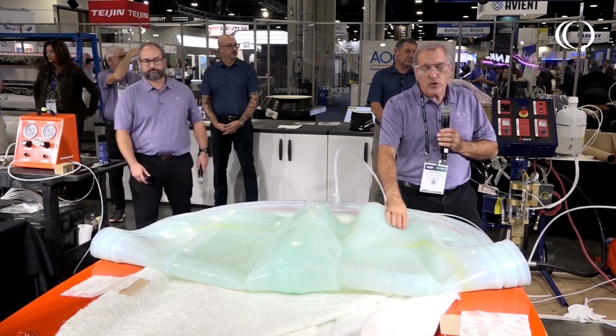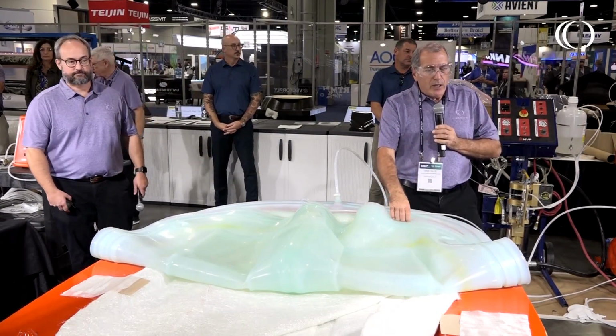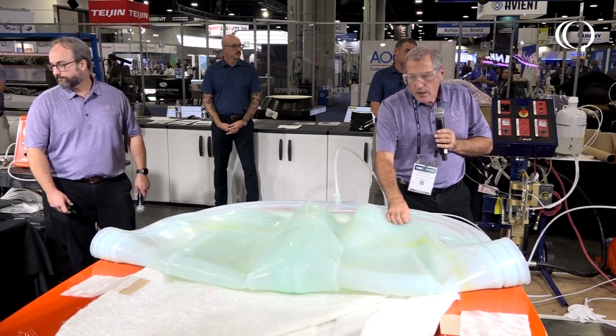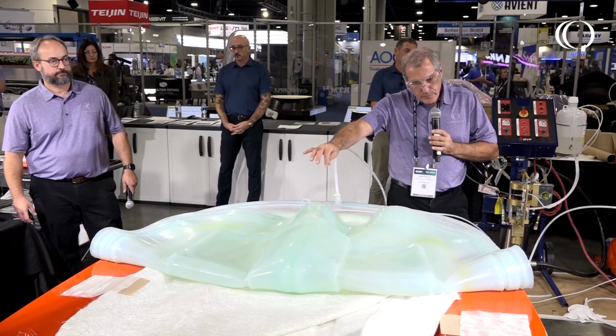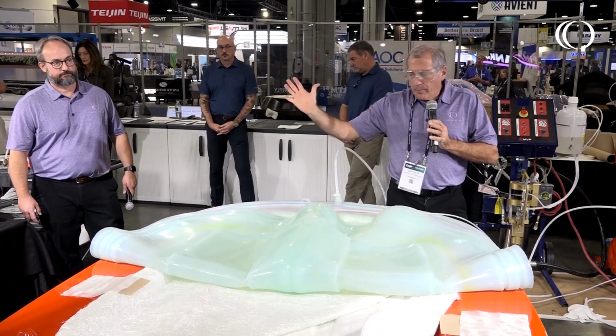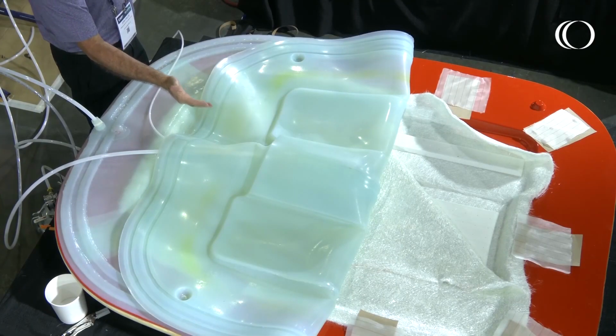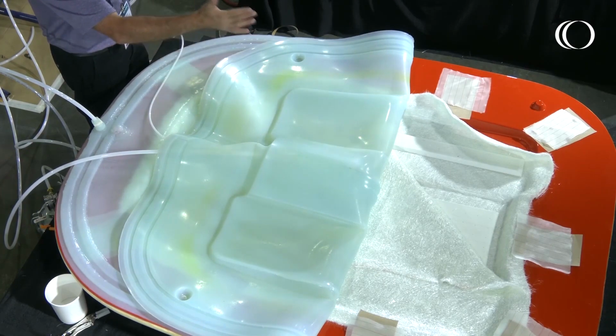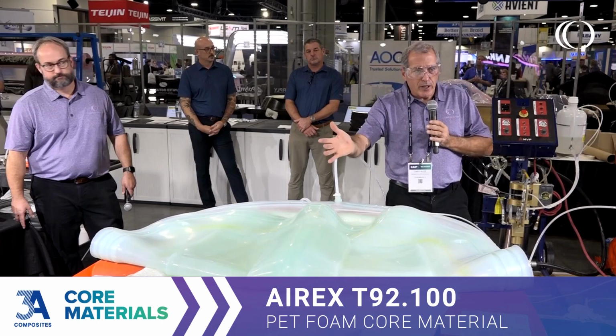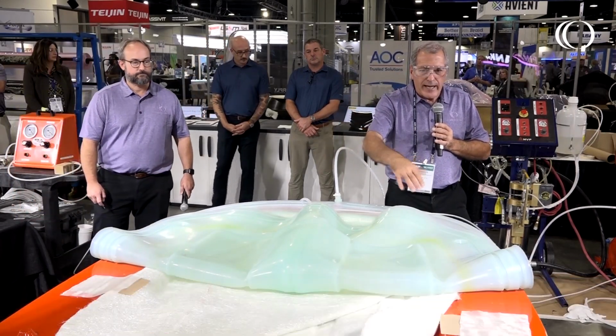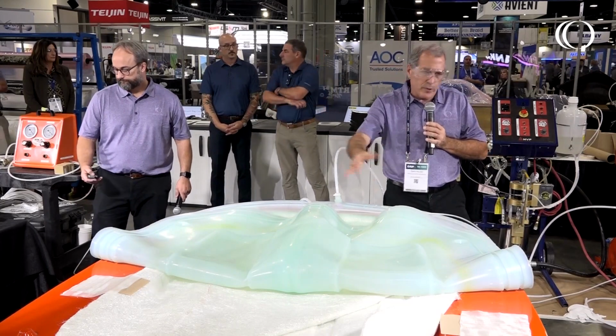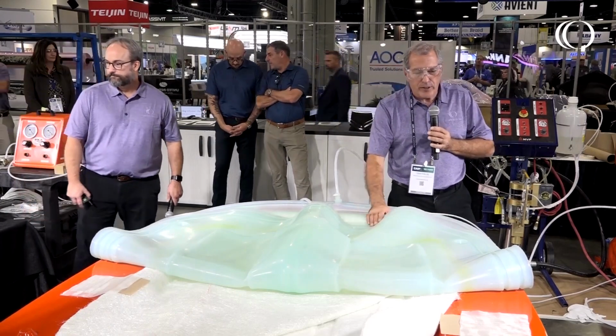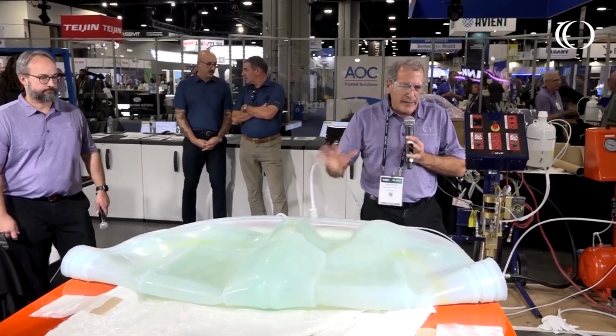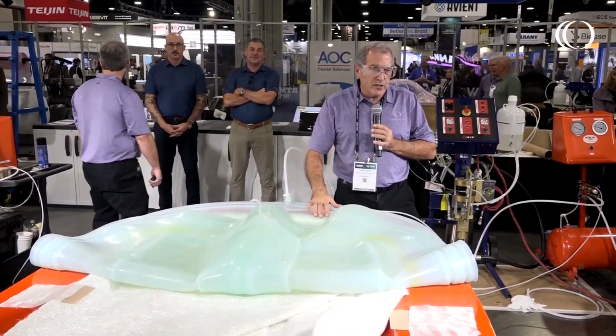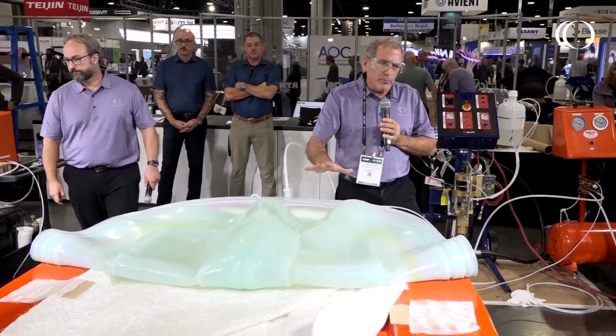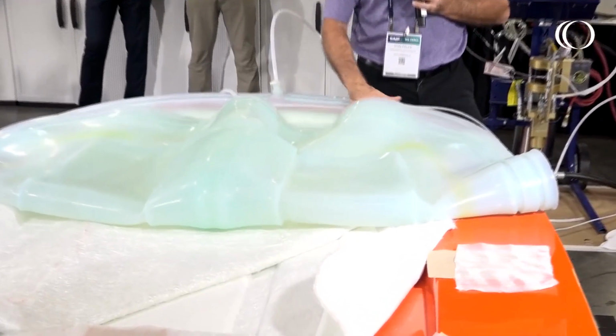Another nice thing about silicone bags in general is they're very easy to repair, they're very easy to modify, and they're also very forgiving. An example of that is this part here, we actually sprayed our bag off of a part, and in our imaginary world of hard tops, we decided for some reason we needed a little bit of stiffness, a little bit of reinforcing in here. So we added some Airtex core material in here just because, and we're still able to use the same bag. So the bag has enough forgiveness and flexibility that it'll stretch around these 3 pieces of core that the bag wasn't intended to do in the first place. So again, it makes making modifications easy, making repairs easy. So it's a system that works great, especially when you're running small to medium-sized parts like this. It's an excellent system to use.